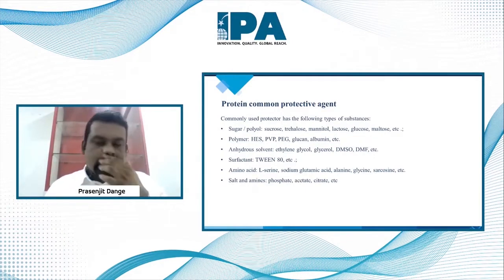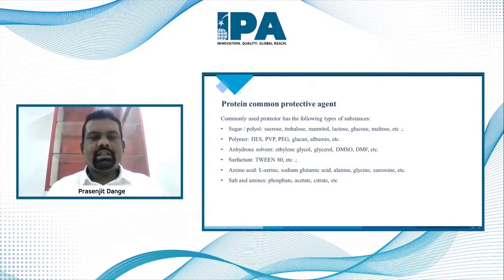So basically, freeze drying as a process itself requires a low-temperature protection mechanism that we have to adopt, because, as I said, the freeze drying process has a variety of stresses on the drugs. These stresses can be differentiated as the low temperature or freezing stresses and the drying stresses, and they can result in the formation of dendritic ice crystals, an increase in the ion concentration, a change of the pH value, and phase separations.